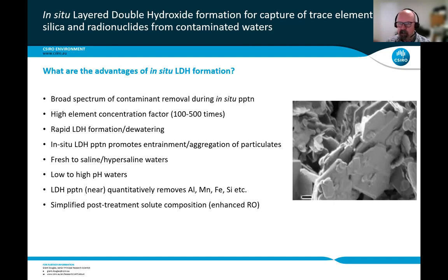And that's really, really useful, that you've got something that takes out a whole lot of metals, but you can also take out a lot of the turbidity and on occasion some of the dissolved organic carbon. One of the other really good characteristics again is you can use it from fresh to saline to hypersaline waters, and I'll give a few examples of low to high pH waters where these have been used. The layered double hydroxide precipitation can also near quantitatively remove a whole lot of elements, and these are typical foulant elements that you'll be familiar with in RO. And so what we get is a simplified post-treatment solute composition. So we've removed all of our foulants, and that can only mean good things in terms of enhanced RO performance.